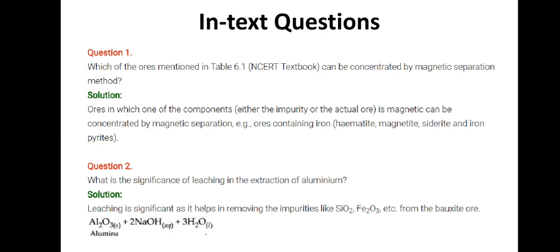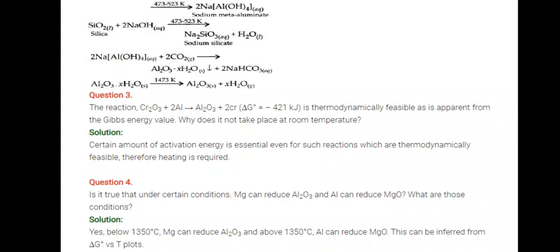The reactions are: Al2O3 solid plus 2 NaOH aqueous plus 3 H2O liquid at 473 to 523 Kelvin will form 2 NaAlO2 aqueous, which is sodium meta-aluminate. Then silica reacts with 2 NaOH aqueous at 473 to 523 Kelvin to form Na2SiO3 aqueous, which is sodium silicate. Then 2 NaAlO2 aqueous plus 2 CO2 gas will form Al2O3·xH2O precipitated plus 2 NaHCO3 aqueous. Finally, Al2O3·xH2O at 1473 Kelvin extracts Al2O3 and H2O.